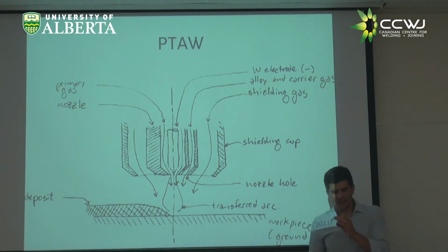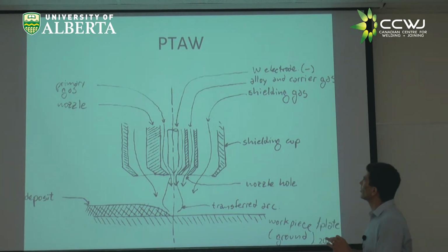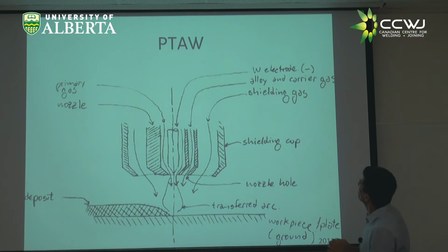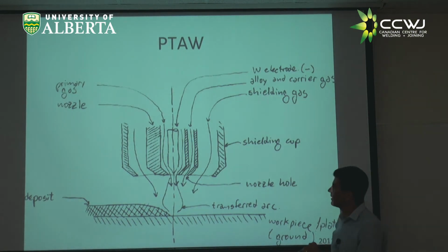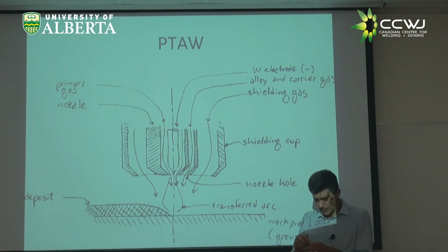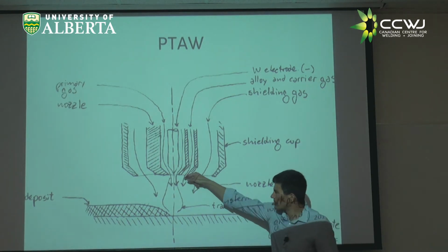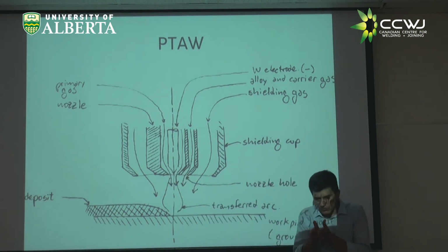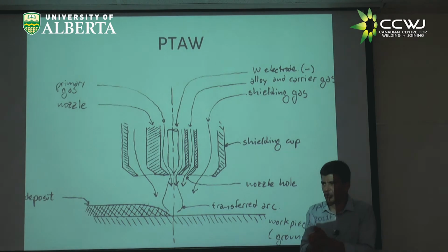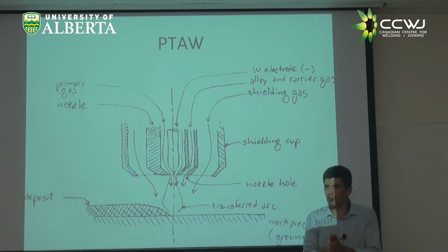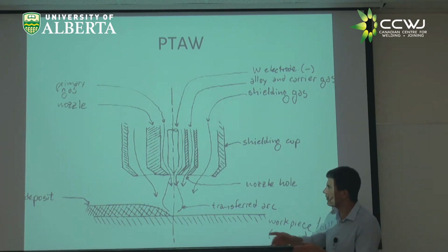And what they did is they encased the electrode in a nozzle, and they blow this secondary gas, right? This, what do we call it? This is the primary, what they call the primary gas, not secondary, the primary gas. So as you blow this primary gas at a pressure, you make an arc that is constricted. Right? If you remember the arcs that you saw in the videos about TIG, they were like a bell, right? Like a Liberty bell, right? Like big. But in plasma, because you're having this primary gas blowing very strongly here, you constrict the arc, and the arc becomes even more of a scalpel, right? Now it becomes so narrow that it can compete with laser, right? It can be very, very focused, right?